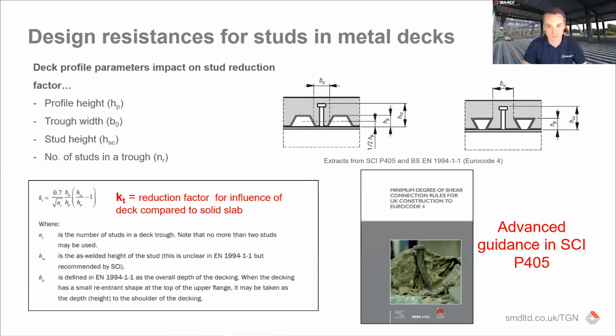So the code, and this is all Eurocode 4 references, as you'll see from the bits down the bottom here. The code utilizes the profile height, the trough width, which depending on your profile type is either your average width of the trough that the stud is welded in, or the thinnest width if we have a re-entrant like our R51 plus profile. So those two are very much about the geometry of the profile and how much concrete do you have around the stud. It's then about the stud height, so what protrusion do you have above the deck, and the number of studs in a trough, which does surprisingly impact considerably the reduction factors. And I'll talk a bit more about that in a moment.